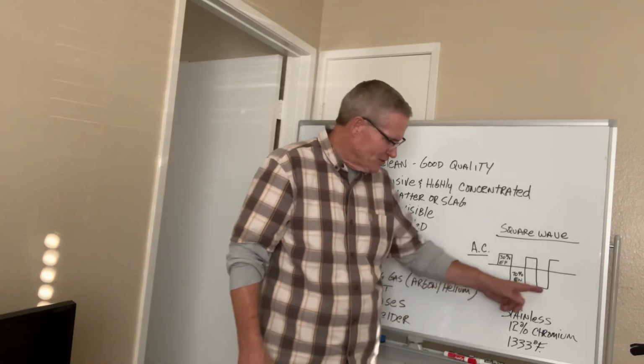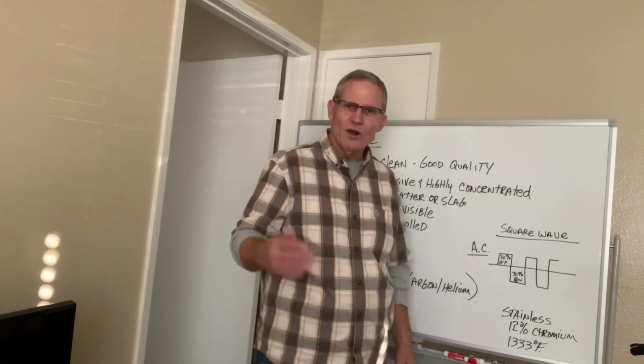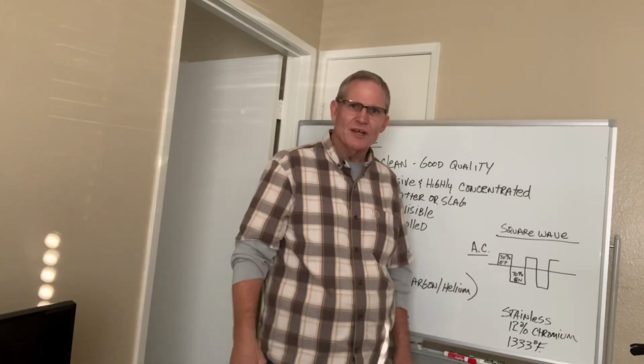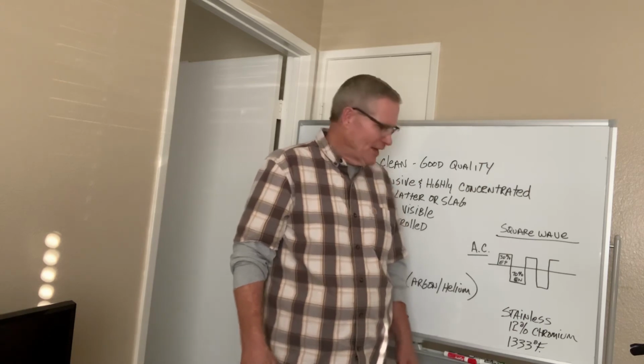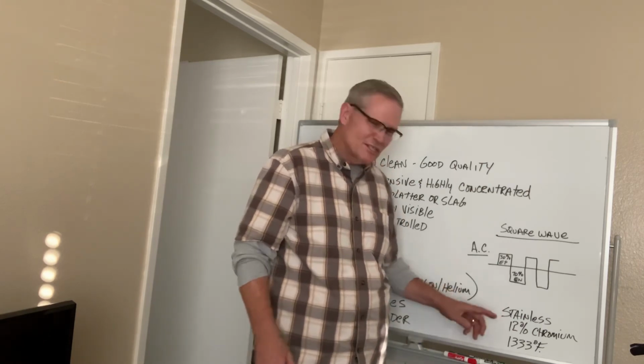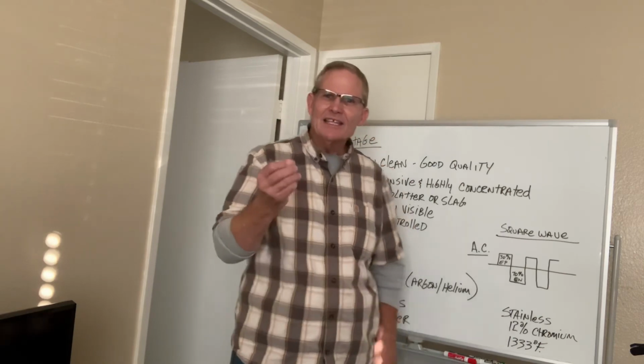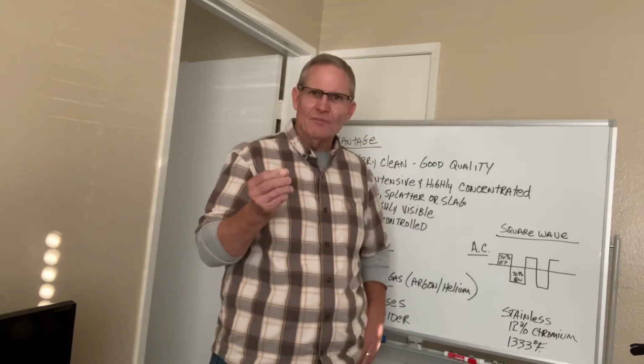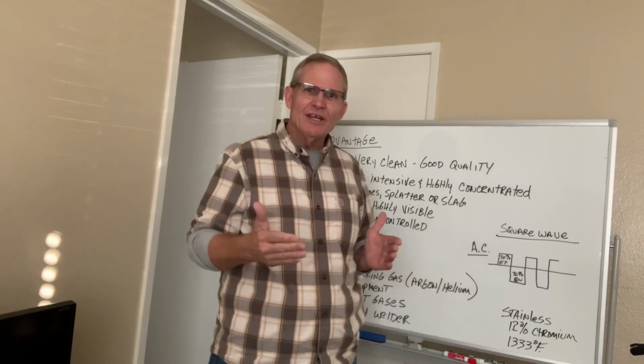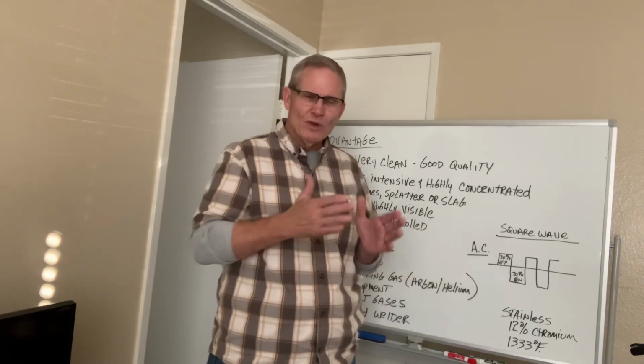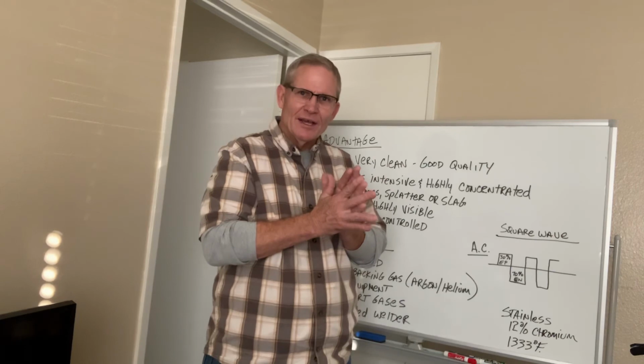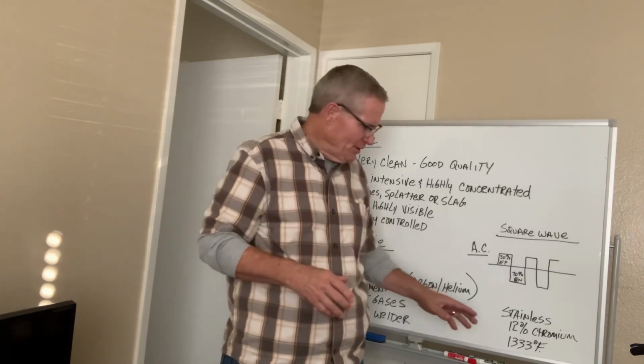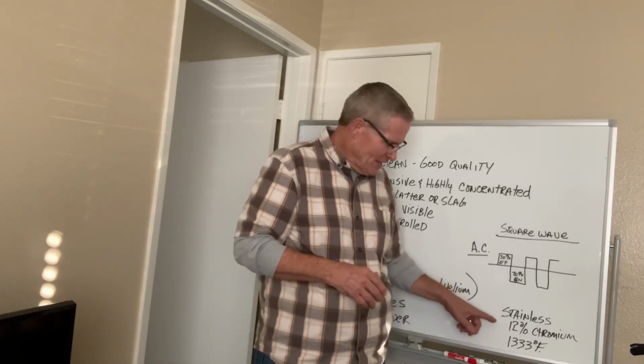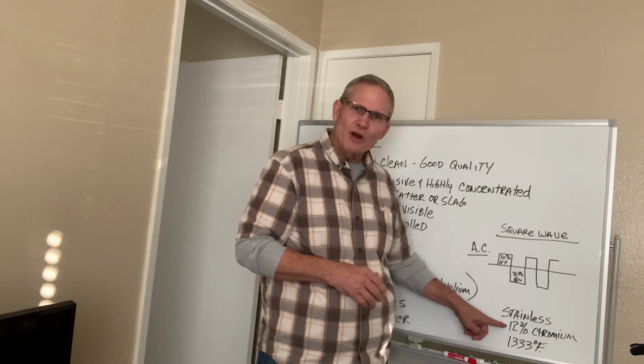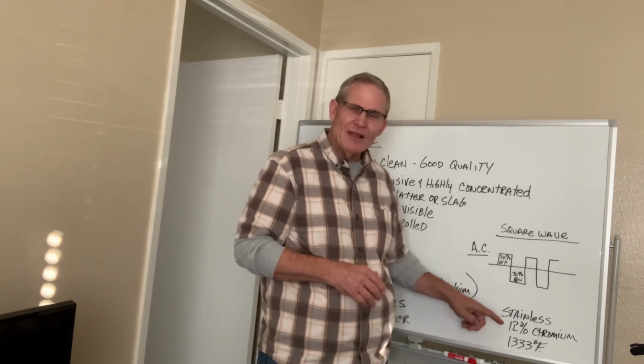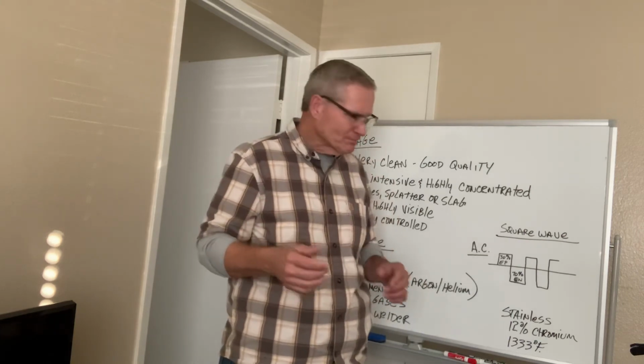My last comment to you is on stainless, because we are going to be welding stainless as part of this process. And the interesting thing on stainless, just for something to keep in mind, is I can take a regular mild steel, and the moment that I reach the 12% chromium zone, I enter into the stainless families. And that's where you get into trouble with stainless, and that is overheating the stainless.